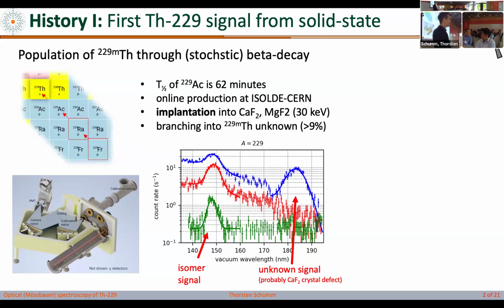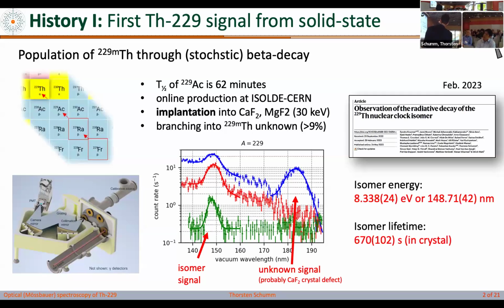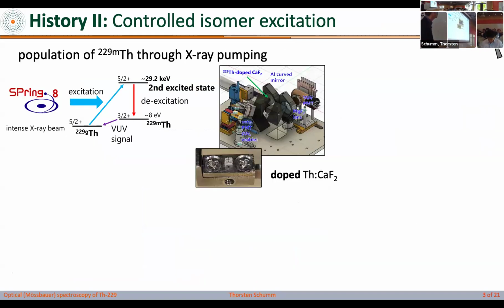These were actually two different types of material. This is calcium fluoride and magnesium fluoride, standard materials in UV optics. They're the ones that are transparent in this kind of wavelength. Okay, and from this they concluded the isomer energy and also the lifetime. And the lifetime, as it was said already, is of the order of 10 minutes. Ten minutes for an excited quantum state to fall down through spontaneous photon emission. That's quite a long lifetime. Good. So we've seen that one.